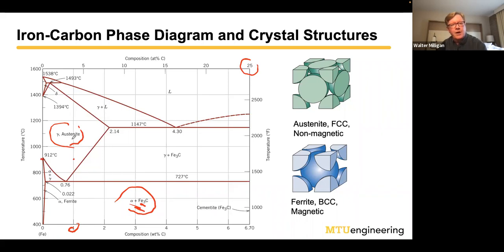The carbides have been dissolved. The carbon is evenly distributed in solid solution, so it's nice and uniform and homogeneous. The crystal structure has changed to face-centered cubic. The good thing about this is if you can heat the material up to that temperature, you can dissolve whatever garbage you had there before from the steel mill or whatever. And now you have complete control over what the microstructure is by controlling the cooling rate.